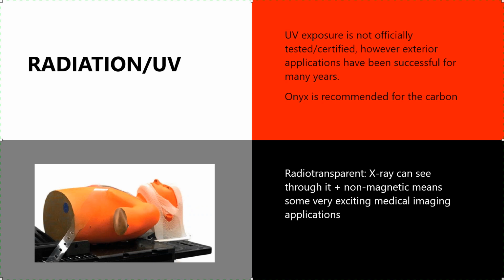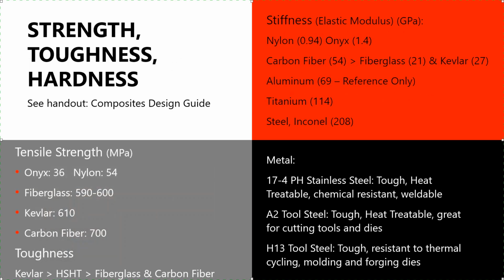A nice little side effect is that ONYX and nylon are radio transparent, meaning the X-ray machines can see through the materials. So if you've got a cast, or one of those halos or a brace that helps fix a shattered bone, if you make it out of ONYX instead of a metal, you can then image it with an X-ray machine. You can put it in an MRI because it's non-magnetic. So there are some really exciting, very structural applications in medical. We're not looking at things like inserting into the human, although some of that might be going on. But for those structural designs, where it's really more of a mechanical design than anything else, we're seeing that a lot.